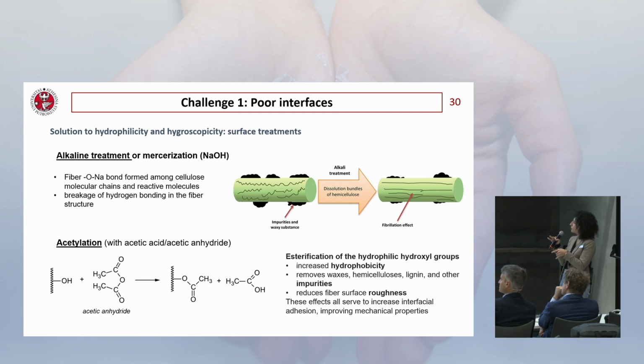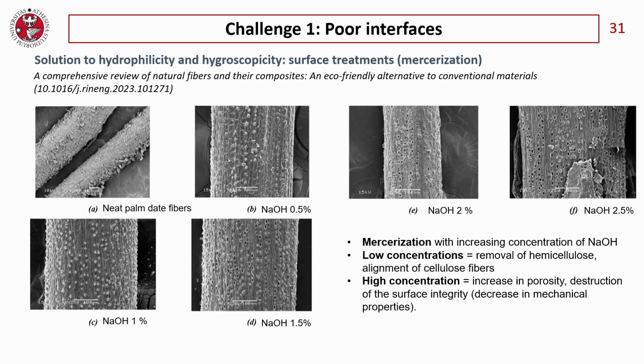What they do is, in one case, the breakage of hydrogen bonding in the fiber structure, and in the other case, for the acetylation, what we are aiming at is an esterification of the hydrophilic hydroxyl groups, and to substitute them with something else, as you can see here. For example, here you can see the different treatments of typical date palm fibers. You can see how the morphology is changing by increasing the concentration of NaOH in the solutions.